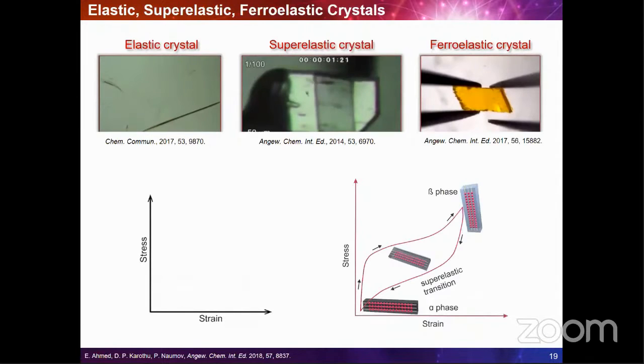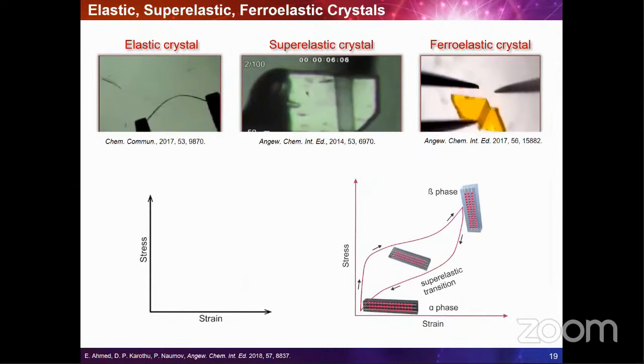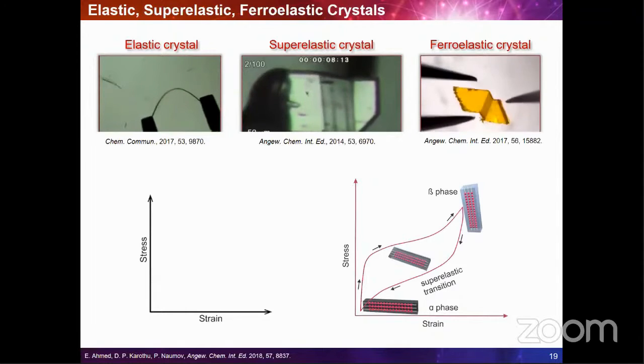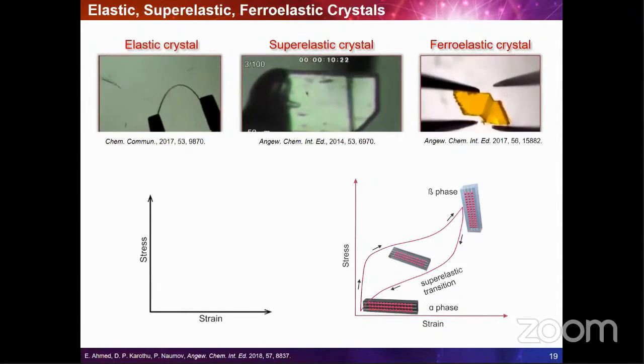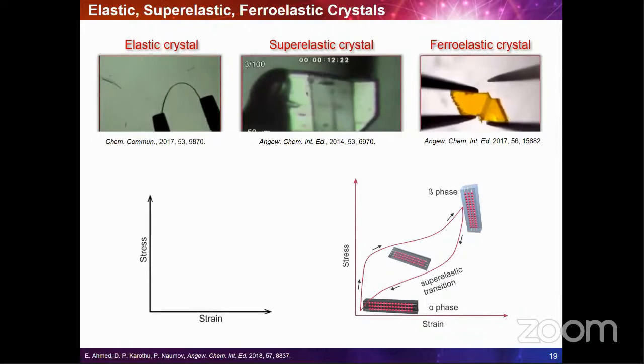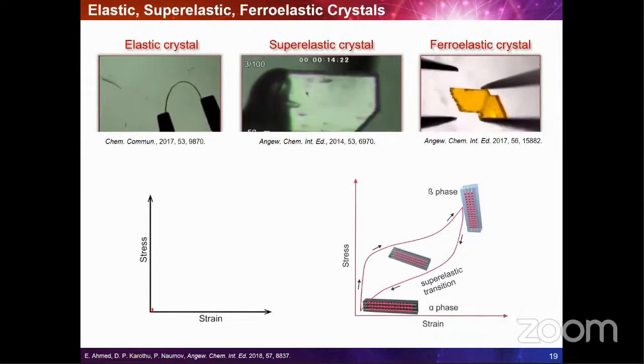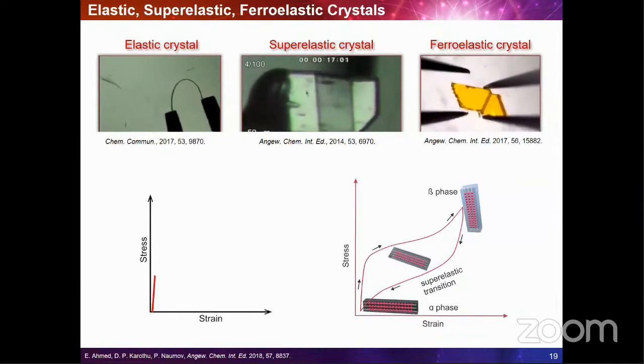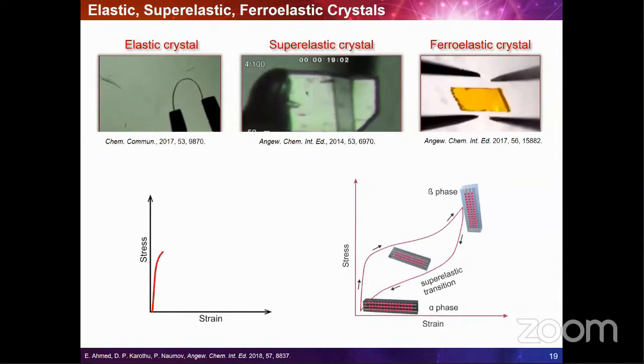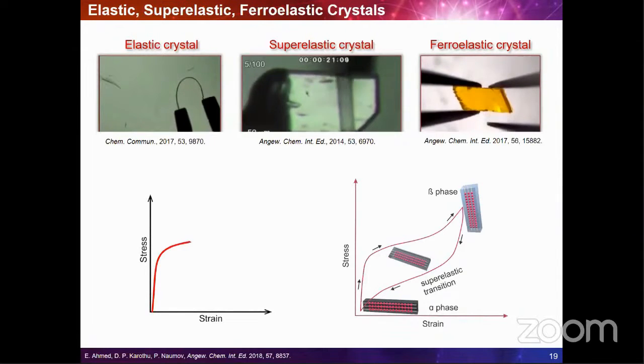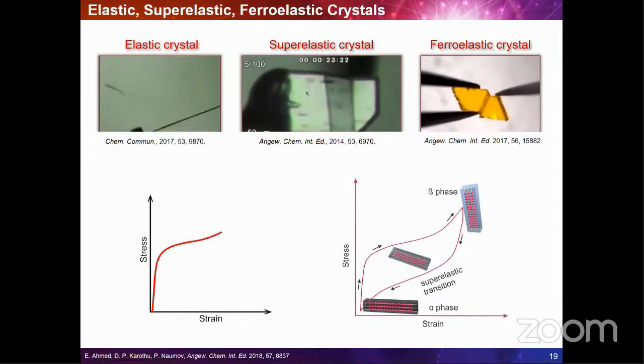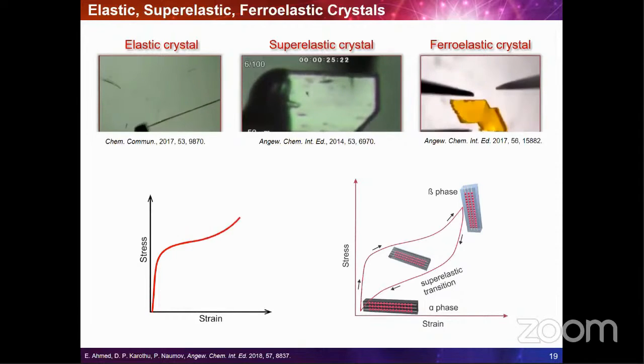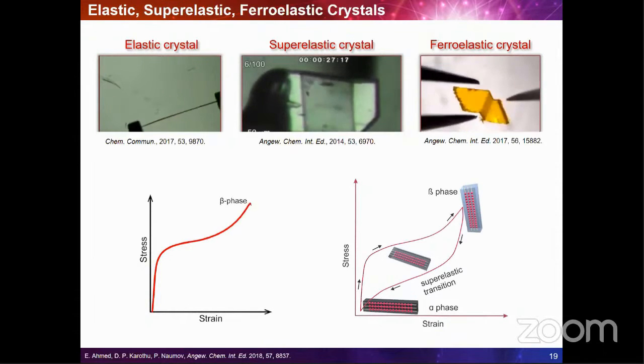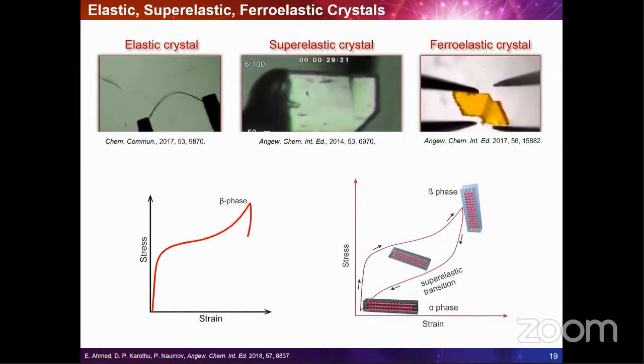Also, there are a number of other phenomena that have been reported in the past, which are really quite surprising and could also be potentially useful. As you might be aware, a typical elastic material does not undergo structural phase transformation under applied force. In fact, elastic materials show modest strain of only up to 2% for metals and only about 4% for molecular crystals. If you apply additional stress, this will result in fracture of the material.